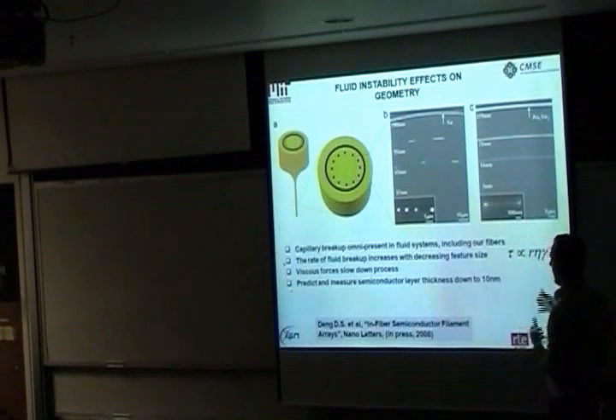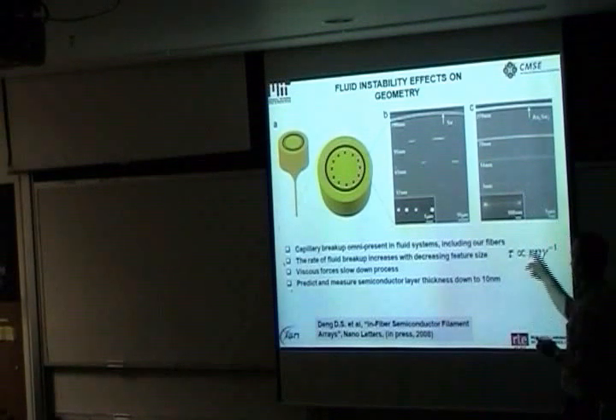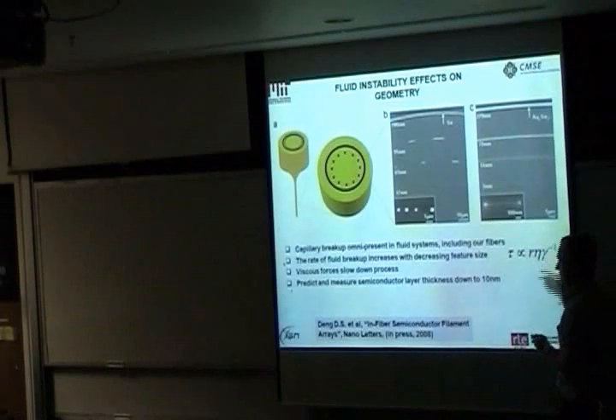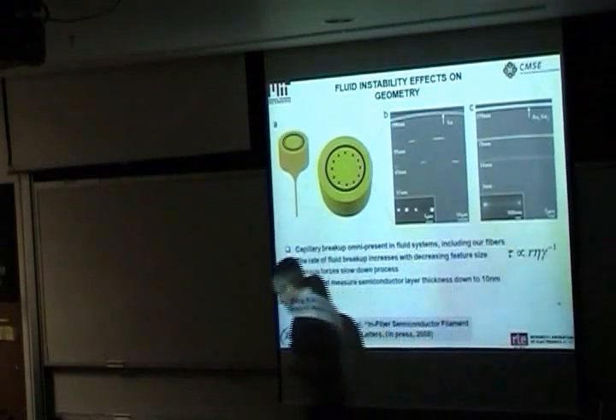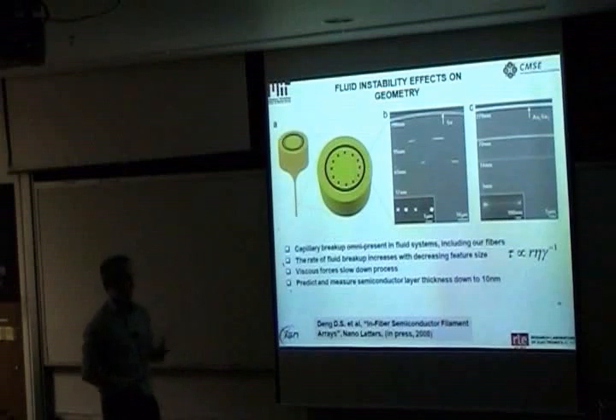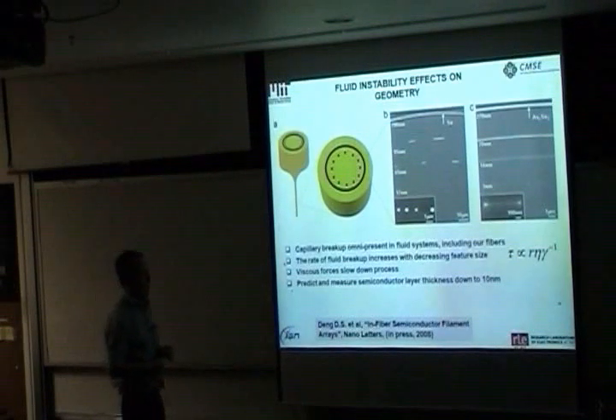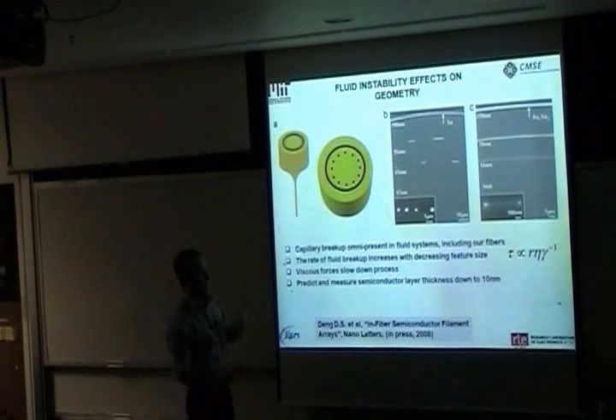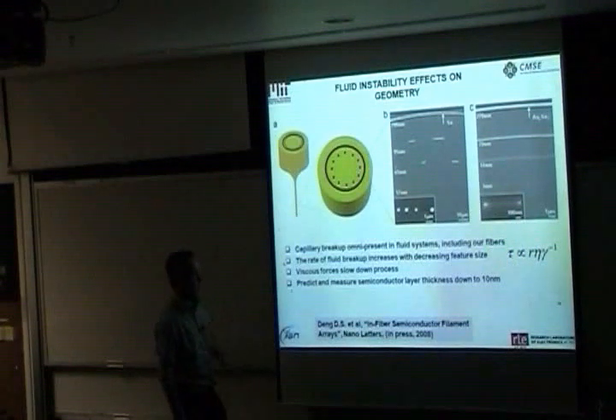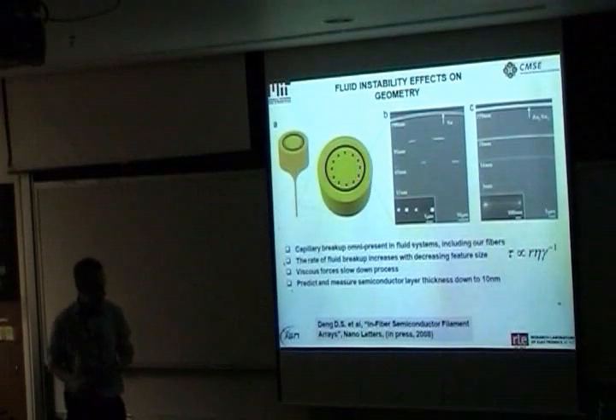And this has to do with the time scales associated with the breakup, which go like the feature size and scale as the viscosity. Selenium is a very low viscosity material when it heats up, and the time scales for breakup turn out to be very short, and there have been a number of papers on this topic.